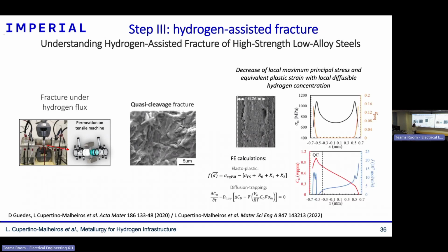And now again, I couple it with finite element calculations, now considering elastoplasticity, but also diffusion and trapping. And here I was interested. You can see here an overview of the fracture surface. On the side where hydrogen is entering, we do have this quasi-cleavage fracture. And on the other side, you just have ductile crack propagation.